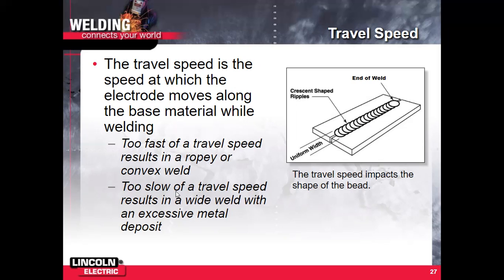Too slow of a travel speed is going to result in a wide weld. So this weld here will basically get overheated on the top of the base metal. It'll puddle out, kind of like you're melting a chunk of ice, and it just creates a big puddle. That's kind of what's going to happen. When we overheat that base metal, the weld's going to become too wide. It's going to be hard to control. Anything outside of a flat position is going to be very difficult to weld. So keep our travel speed up, but also maintain that balance between penetration and travel speed and heat. That's one thing we need to be aware of. This is all what's going to come in time as you develop your skills.